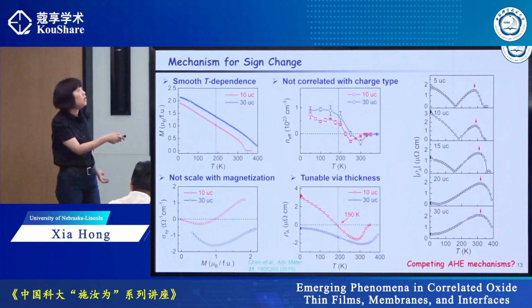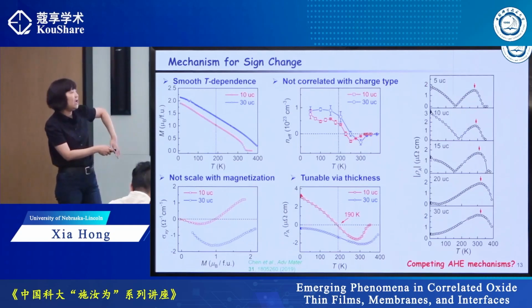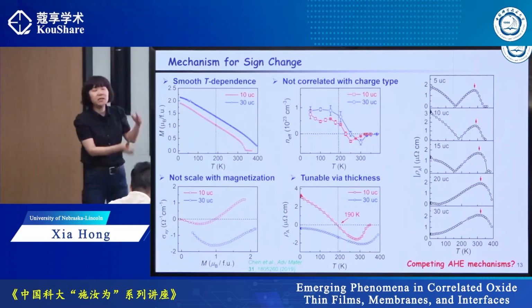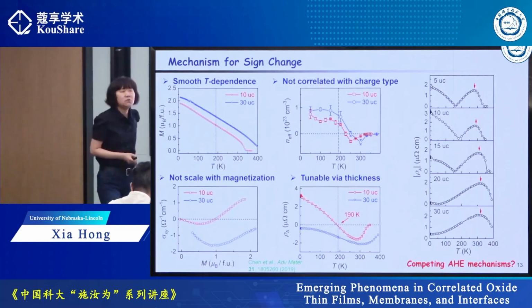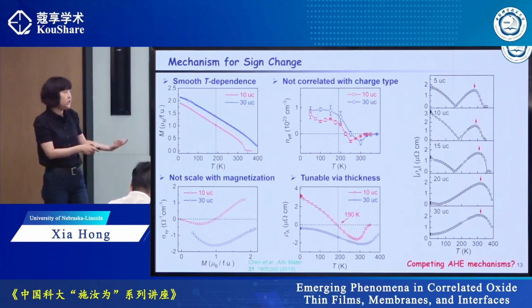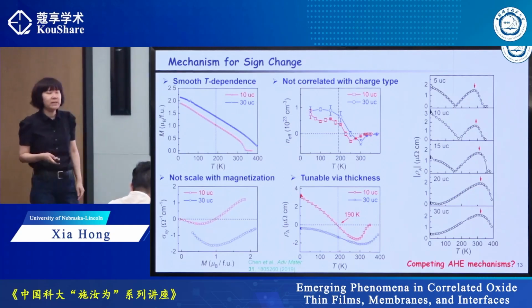And for all the films, they have a similar temperature dependence. So it's more likely I have anomalous Hall resistivity that increases with temperature, and it has shifted by a universal flow. And depending on the competition between these two effects, some samples will have a sign change. So the sign change is really due to the competition of two anomalous Hall mechanisms.